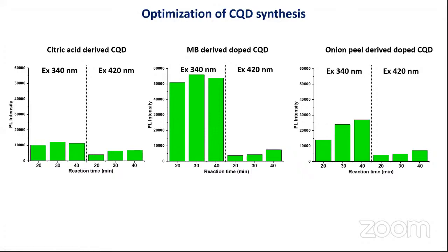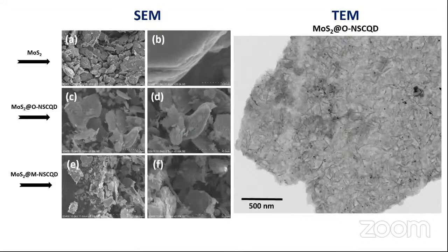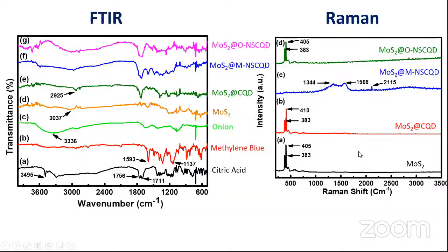Thank you. So this is the SEM and TEM image which confirms the presence of the doped NS CQD on the MoS2 sheet. And here in that TEM image, we can see there is a carbon deposit on the MoS2 sheet. So here are the FTIR and Raman spectra, which show the fingerprints of our synthesized CQDs.